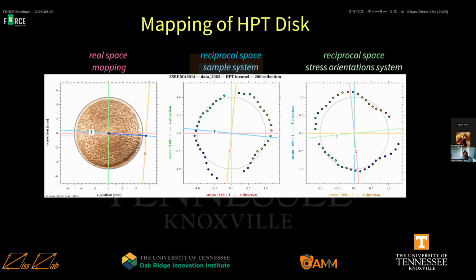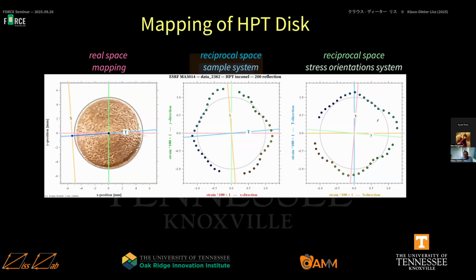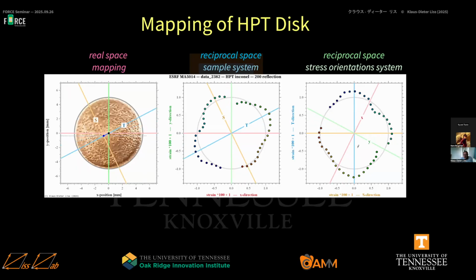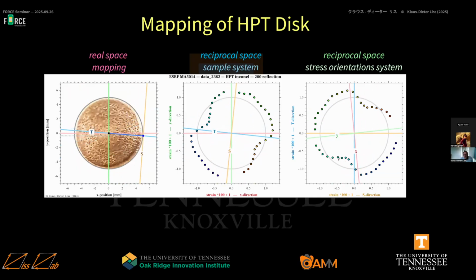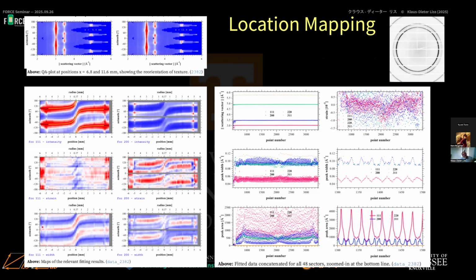But when we look to the right figure here, we see that the maximum and the minimum with respect to shear remain constant. So we can evaluate that. What I did is we record patterns here as to the right here. So diffractograms, Debye rings, and then we stretch them out as a function of azimuth, the azimuthal angle when we go around the ring. And this is the radius, basically, the value of the scattering vector. When we see the first reflection in the FCC, this is a 111 reflection, this is a 200 reflection, this is a 220 reflection, and then comes other 311 and so on.